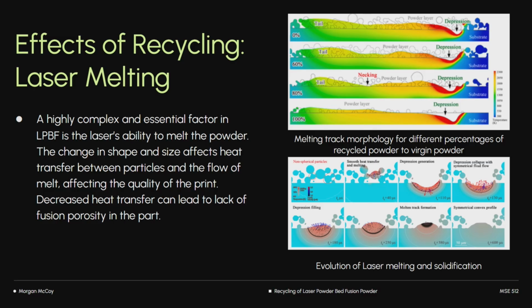On the right, we have two views of the laser melting process. Here at the bottom, we have a head-on view where you can see how initially there's a divot and then it bulges up. And at the top, you can see a side-on view of that same process with 0, 60%, 80%, and 100% recycled material. There are some changes between those cases.